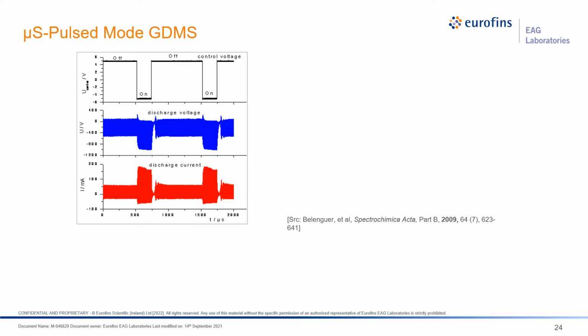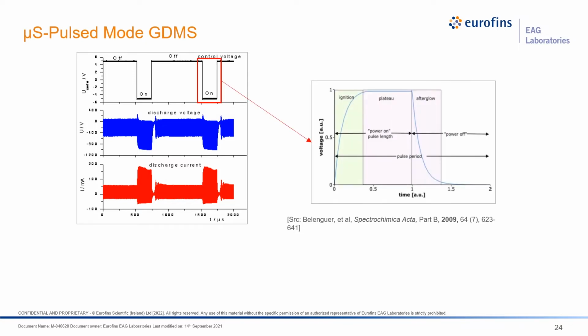The fast flow GD source can operate in two modes. One is continuous DC mode. The second one is pulsed DC mode. In pulsed DC mode, there is a voltage rising, stabilizing, and off period. Two important features happen when GDMS is operating in the pulsed mode. In the plasma quenching stage, or afterglow stage, there is a population surge of argon metastables, which enhances Penning ionization. Second, it generates pressure waves during those pulses, which can affect ion transmission. Dr. Bob Hasterbeck in our facility has successfully addressed many of those ion transmission issues.